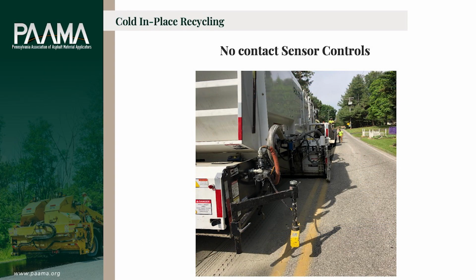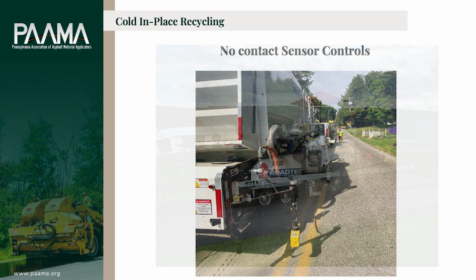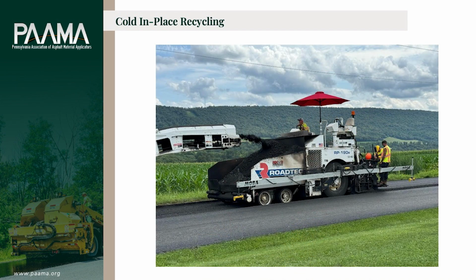The milling machine has sensors on it, those yellow boxes. They're no contact sensors. There's 3 of them, one there, one on the cutting mandrel, which is directly behind it, and one on the other side of the cutting mandrel. So we have a nice cut, a nice plane there. The pavers themselves have no contact skis. You can see that there's sonics on the front and the back of that, also giving us a nice level plane, which gives us a better ride. Another shot of that, the material going into the paver.